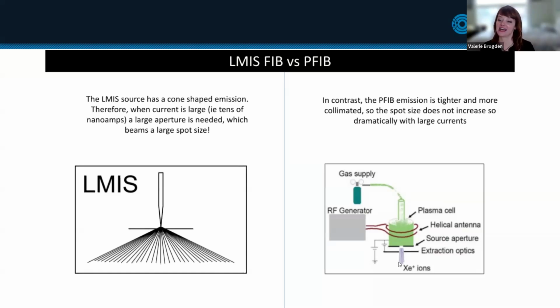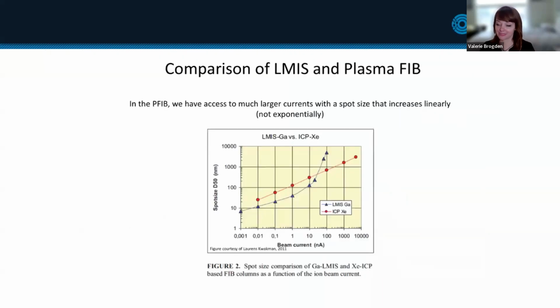So now if we go back to the previous slide, I'll give you the takeaway here. For very small currents, the gallium FIB is a lot better because it has a smaller spot size at smaller currents. But when you use a large current, the PFIB is a lot better because it has a smaller spot size at large currents. So when you're choosing between the two, if you need to make really precise fine cuts, for example the very last phases of TEM prep, that's where you want to use a gallium FIB. But if you have to make giant cuts and the bottleneck is volume removal and not necessarily really specific endpointing, then you're going to want to reach for a PFIB.